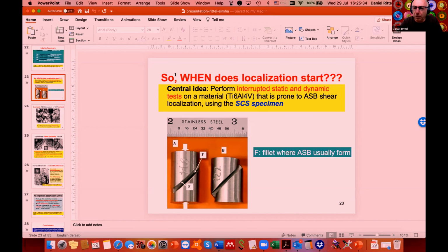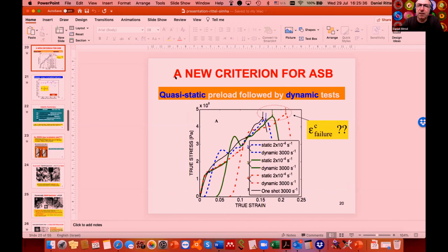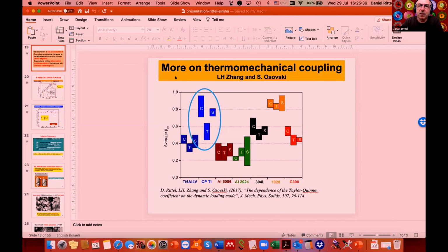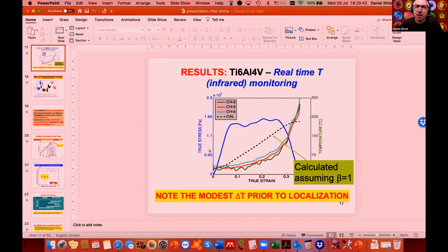Okay, so the temperature increase that I was showing, and we've done tens and tens of experiments like that, including at Caltech, this is typically what we always find. Prior to complete failure, the temperature rise is extremely modest. It's a few tens of degrees. It's only once your shear band has formed that you will see several hundreds of degrees that have been reported long ago by Duffy. But prior to final collapse, the temperature rise is extremely modest.